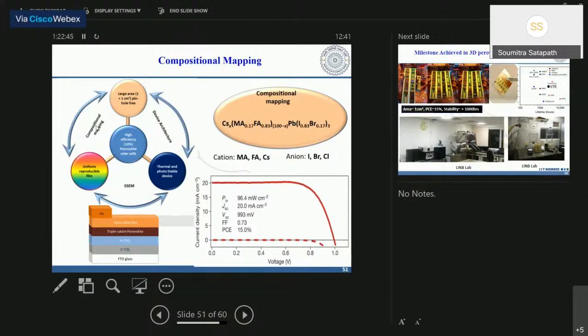Along with compositional engineering and the dual solvent elimination method, we are trying to make a solar cell over a very large area, 1 centimeter square. One centimeter square is considered a large area for a perovskite solar cell, because most reported devices are 1 millimeter square. Using this triple cation perovskite solar cell, we achieved an efficiency of 15%, which is stable over 3 months. This triple cation perovskite solar cell, by compositional engineering and solvent engineering, in a large area, was made completely at room temperature without the help of a glove box. Okay.